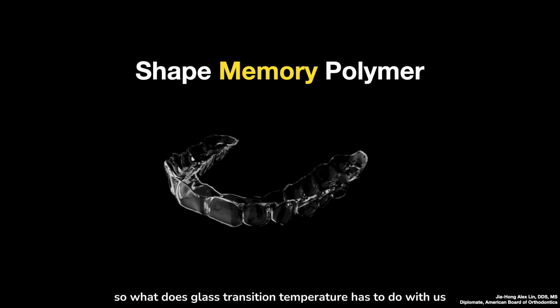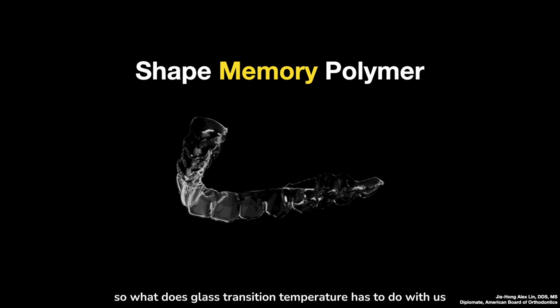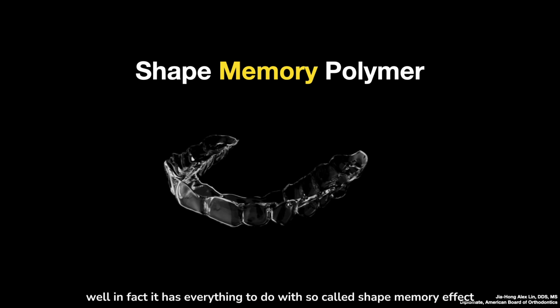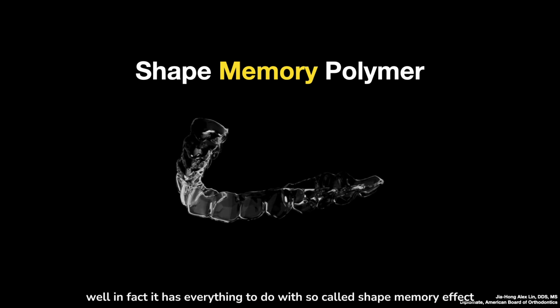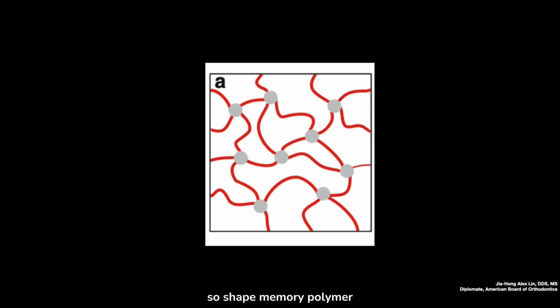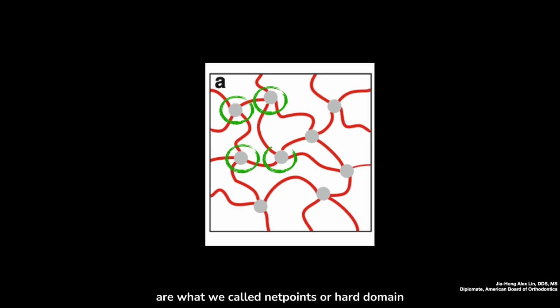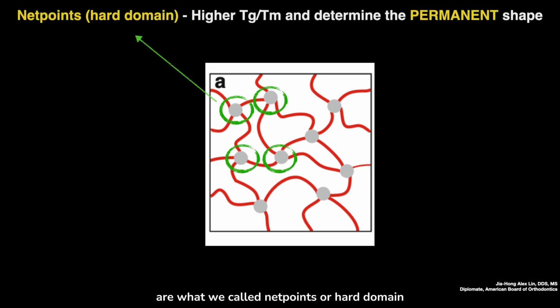So what does glass transition temperature have to do with this? Well, in fact, it has everything to do with the so-called shape memory effect. Shape memory polymer usually consists of at least two components. We can see the green circles over here are what we call net points or hard domain. Now the net points or hard domain usually have a higher Tg and they determine the permanent shape. So that's the shape of the aligner that we want it to be.